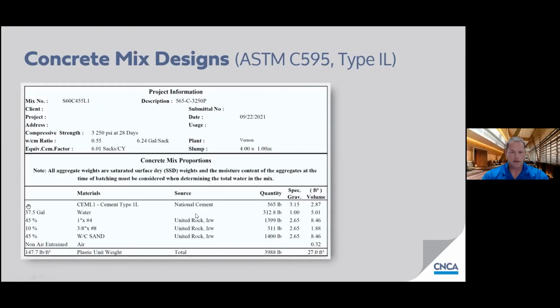To get this C gradation, they use 3 different sizes of rock, a 1 inch by number 4 blend, a 3/8 inch by number 8 blend, and washed concrete sand. And of course, we have some water, we have some air. This particular mix doesn't have any supplementary cementitious materials in it, but it produces nice concrete, 3,250 PSI at 28 days, 4-inch slump. And this kind of a concrete mix is kind of the bread and butter of the concrete producers in our area. I wouldn't describe it as particularly high performance other than by its use of type 1L or Portland limestone cement being a strategy, a tool used in this case to reduce the greenhouse gases for this particular concrete.